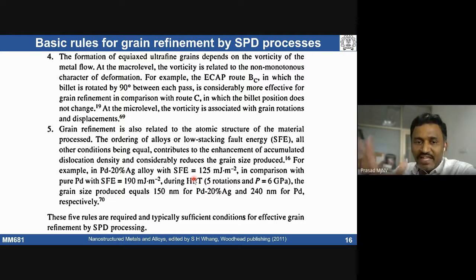Depending on stacking fault energy, the amount of grain refinement is going to be different. If I take aluminum and copper, and apply the same amount of strain, everything the same, which of them is going to have a finer grain size? Relatively, aluminum? Why? Aluminum is a high stacking fault energy material, and copper is a low stacking fault energy material. If deformed under the same ECAP, same route, same amount of strain, copper is going to see a much finer grain size as compared to aluminum.